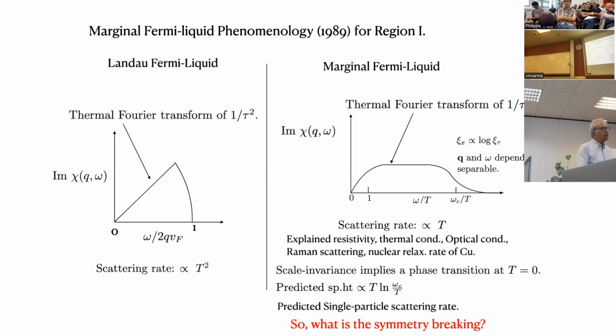Well, obviously this was not working. So a bunch of colleagues of mine and I proposed, it's good to remember that a Fermi liquid is also a scale invariant theory. The fluctuation spectrum is going as 1 over tau squared, where tau is, let's say, if I'm at T equals 0, just the time, otherwise it's a periodic function of temperature too, at finite temperature. Okay. So this is 1 over tau squared, and we in effect said, let's try some object which goes as 1 over tau, which is quite different.